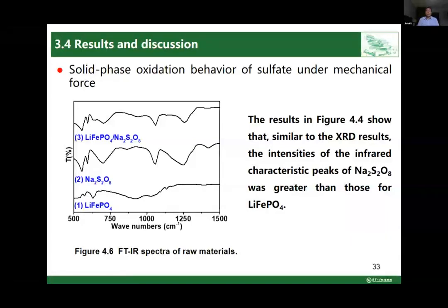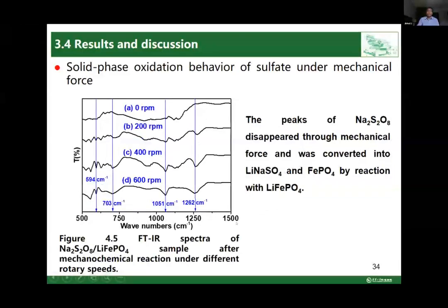And this figure also shows the FTIR spectra of different reaction samples. The result in this figure also shows that, similar to the XRD result, the infrared characteristic peaks of sodium persulfate are greater than those of lithium iron phosphate. So the result of this figure shows that after the mechanical reaction at different rotary speeds, the characteristic peak of sodium persulfate gradually disappears, and new characteristic peaks appear in the infrared spectra.